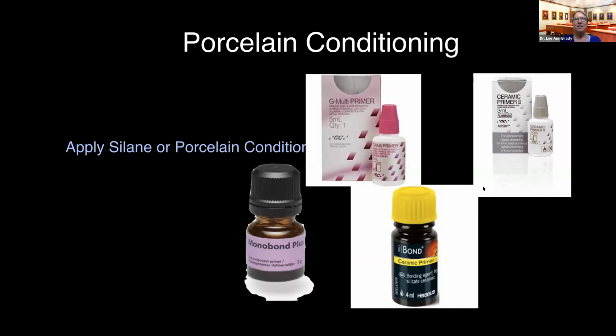Describe the steps in the bonding sequence for EMAX and when to apply the glycerin. So the bonding process for EMAX in my world is going to be: try in, adjust contacts, adjust occlusion, polish everything out of the mouth, 60 seconds of Monobond Etch and Prime, rinse and dry. I am then going to do whatever I do on the tooth.